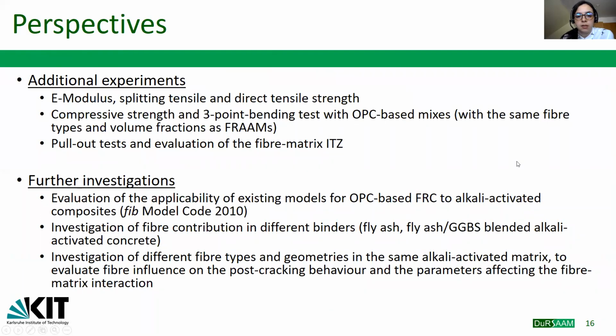From the experimental results of this investigation, it was possible to evaluate the behavior of fiber in an alkali activated matrix, and it's possible to say that the addition of fiber affects positively the post-cracking behavior of the composite, and that different fibers with different geometry behave in a different way. However, additional investigation and experiments are needed.